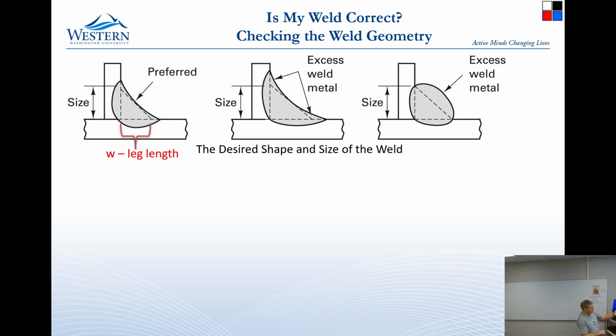So things that you can do, you can over weld where you put too much weld metal on there. That can have a bad function because of the heat affected zone, so you will damage too much of the material around it. So when we heat it up really hot, the grains all grow there, we lose all the strength in the material, and we have too much ductility. And so you may have a very strong weld, but the material all around the weld, we can lose that.